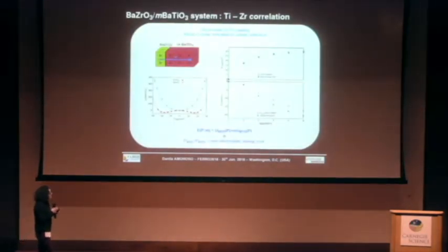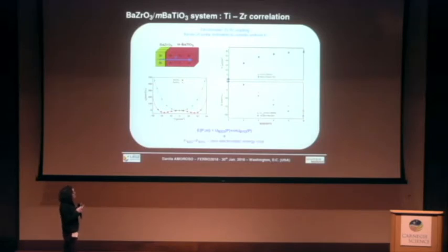The electrostatic coupling makes zirconium active. Why? Because otherwise, an eventual mismatch of the polarization between different layers will produce an energy cost for the system. In order to avoid paying this penalty, the system prefers to sustain a homogeneous polarization all along the chain.